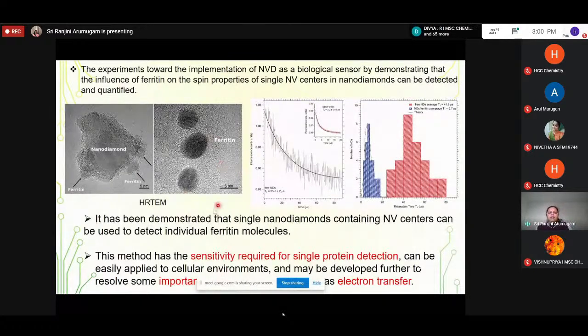On the left, what you see is a high resolution TEM picture of ferritin protein with nanodiamonds. These are the big ferritin globules, and this picture is a closer view of one of the globules, in which the ferritin and the nanodiamond are present. So it's a clear picture of how it is incorporated. And we looked into the T1 relaxation time of the nanodiamond under the influence of Fe3+ from the ferritin. So this is the T1 relaxation time.